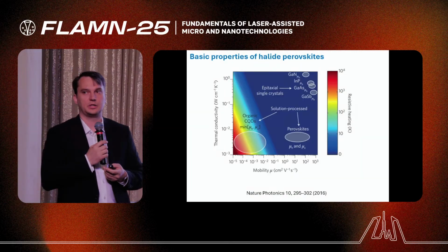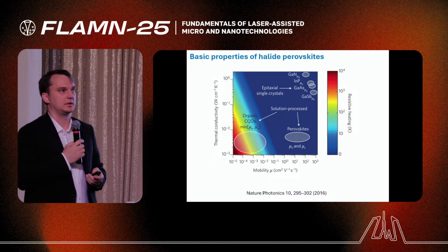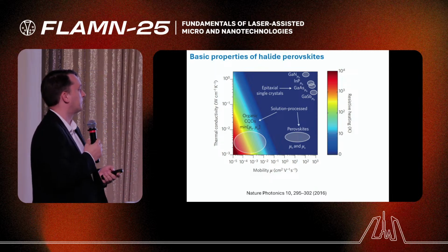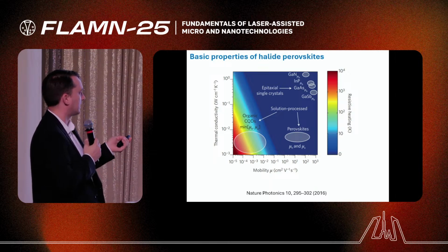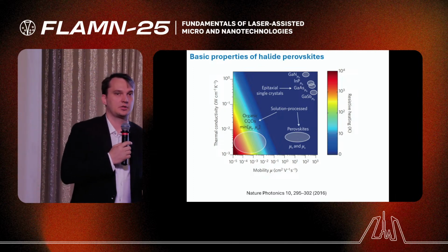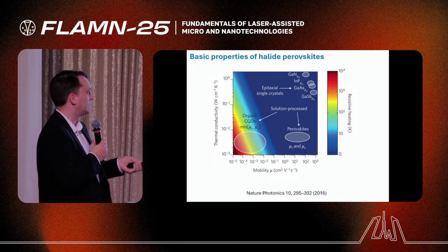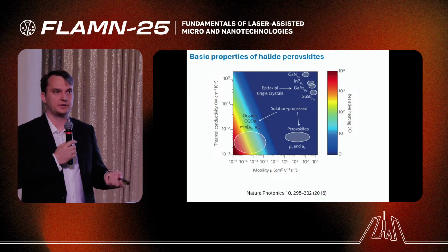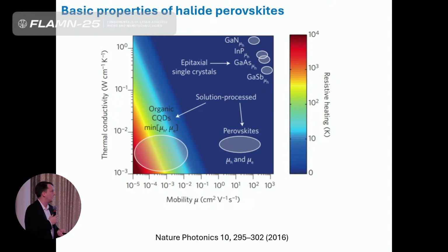And also, as for optoelectronics applications, especially applications like transistors or laser diodes, there are some critical parameters like thermal conductivity and mobility of charge carriers. The mobility of charge carriers in perovskites is quite good, comparable with the family of standard semiconductors like III-V and II-VI. But thermal conductivity is much less. It's close to glass, even less than glass. On one hand, it's bad if you would like to create a high power device, because of the overheating problem. But from the point of view of laser ablation, it's good. I will show you many examples of how we can employ this.